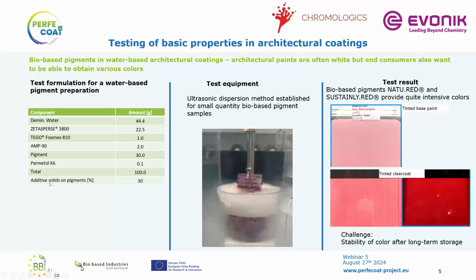So you have on the left side a pigment preparation, basically some water and additive to stabilize the pigment and avoid foam creation, neutralizer for the pH, and then the main pigment. We used specific test equipment due to the small quantity of raw material that we obtained. Typically in the industry, we would not use such equipment. Here it's an ultrasonic equipment. We would use a disperser and we would have a large amount of pigment preparation, like half a liter or a liter. Here we're working on this picture with a 50 milliliter sample.